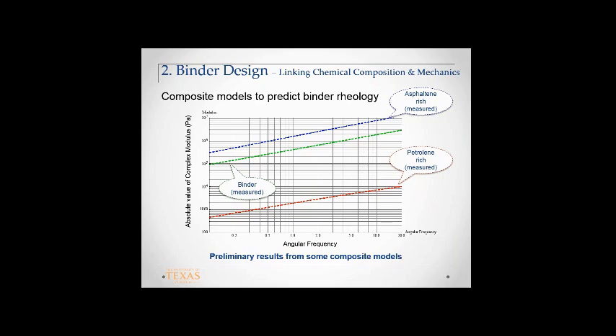Now the question was, can I take these properties and those properties and use some kind of composite model to predict what the binder properties are? Sure enough, you can. These are the two bounds of the composite model, the upper and lower bound. Based on using these numbers, the petrolenes and asphaltenes, we are trying to predict what this G star should look like, and comparing these predictions to the measurements over there. So it seems like it's working very well, but it's not as robust. There's still some falling off at this end on a log scale. So we're trying to fix that, and I think that's where a little bit of composite modeling helps. This looks small, but it's on a log scale, so it's pretty significant.